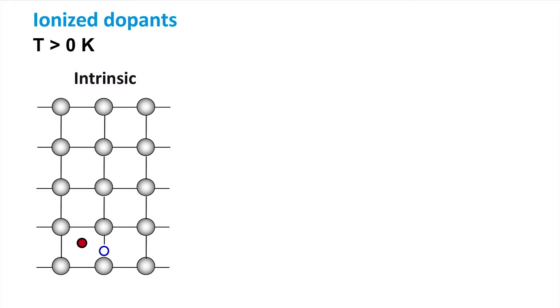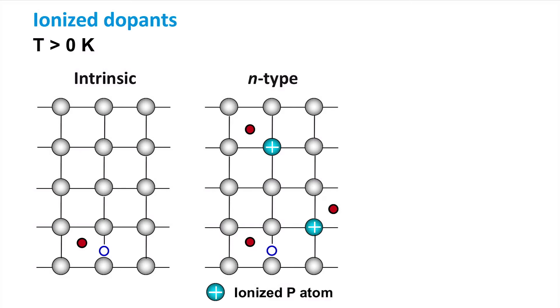The same process of breaking bonds also occurs if the material is doped. However, in doped material, thermal excitation also affects the dopant atoms. In n-type materials, the extra phosphorus electron needs a very small amount of thermal energy to get loose from the phosphorus atom and become mobile. Hence we say that the phosphorus atom donates a free mobile electron into the silicon lattice.